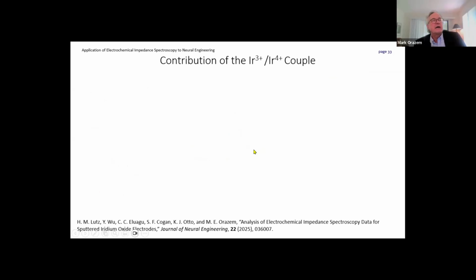I want to tell you a little bit about how we developed that model for the iridium. If we're looking at iridium oxidation, in the potential range we're working with, we believe that we're really going from 3+ to 4+ and back. And so we can describe this as a reaction. The total concentration of 3+ and 4+ cannot change. So this is the total concentration. And we can define a gamma, which is the fractional coverage of the iridium 3+, relative to the total amount of iridium, which would be the sum of 3+ and 4+. We can write a rate expression for the reaction going in the forward direction and the reaction going in the backward direction, written here in terms of this gamma.